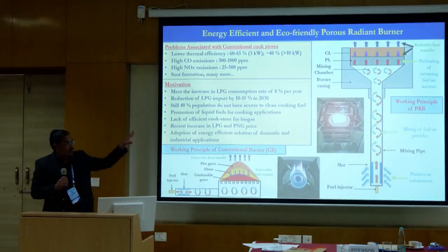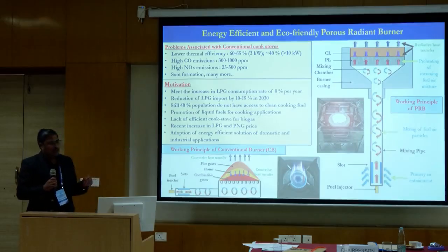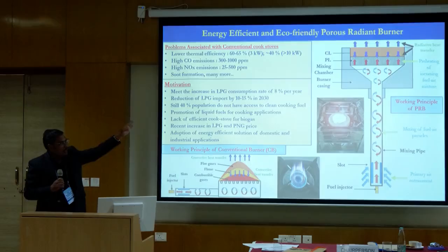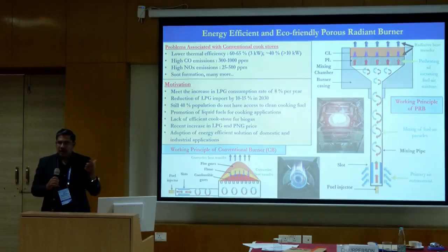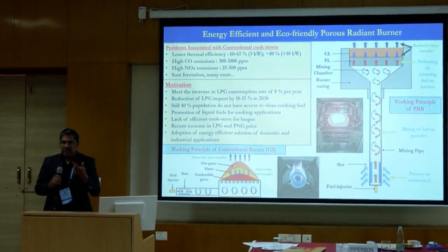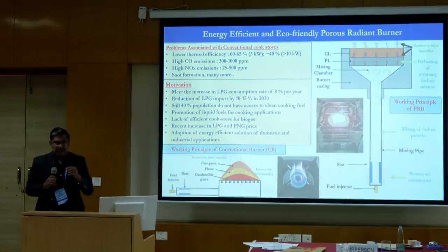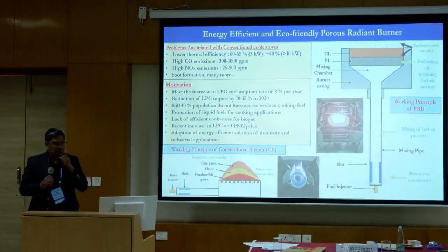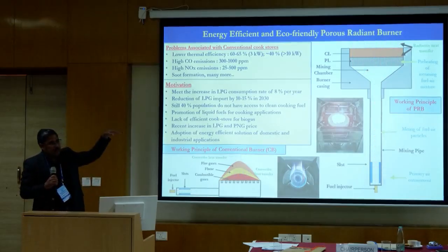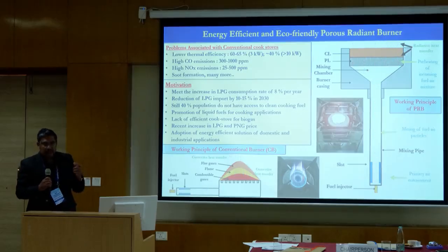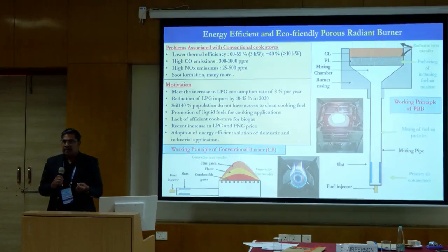With that concept, we have developed the so-called two-layer porous radiant burner. You can see here on the right side, the brownish color is the combustion zone, which is made up of high thermal conductivity, high emissivity ceramic material. This is SiC, topped with some material which has an emissivity in the range of about 0.9 to about 0.96. Below that, where the white line is, it is made up of a low thermal conductivity, low porosity alumina matrix. Basically, the lower layer acts as a flame arrestor.